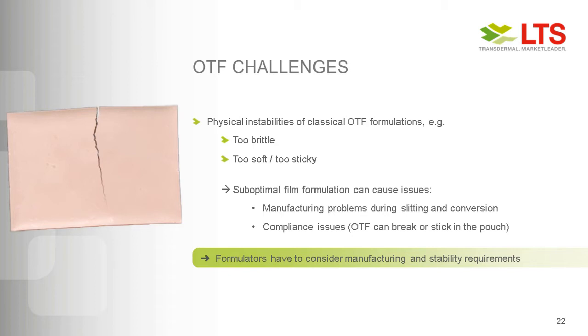Either they cause issues during manufacturing, especially during slitting and conversion, because either everything breaks or everything sticks to all the toolings, or it can create compliance issues with the patients, especially if the OTF is broken in the primary packaging and the patients maybe only take part of the OTF, so they have an incomplete dosing, or the OTF sticks in the pouch, and it really makes it difficult for the patient to remove the film from the packaging material and also to have the right dosing. So the formulators of OTFs always have to consider the manufacturing and the stability requirements of OTFs, because they might look different than the film right after formulating it.